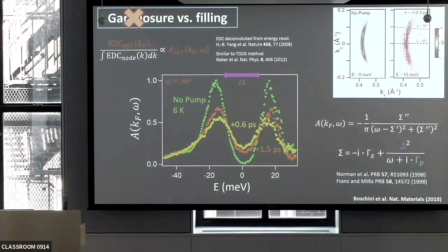So the kind of experiment I would like to do is an experiment that allows me to tell whether I'm having pairing in momentum space or pairing in real space. Am I observing a BCS to BEC crossover type situation? I would like to be able to distinguish between these two scenarios. Yeah, I fully agree with you. This is not directly an indication of superconductivity in a thermodynamic sense. Just looking at a spectral feature changing, usually we associate it with superconductivity, but indeed it could just become very incoherent and you still retain a pseudogap.